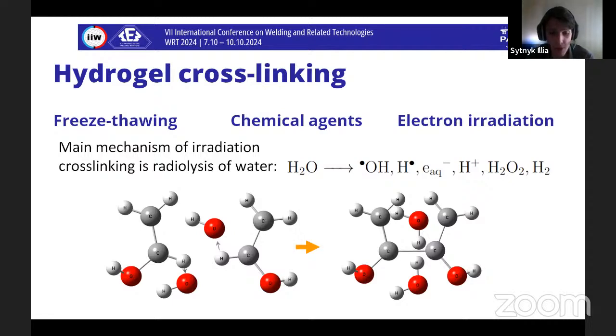In case of electron beam irradiation of hydrogel material, accelerated electrons are almost completely absorbed by water, which constitutes around 85% of its mass. Of the three main reactive forms that are produced in water during irradiation, which are hydrated electrons, hydroxyl radicals, and hydrogen atoms, hydroxyl radicals have the greatest impact of transferring reactivity from water to polymer chains. They detach hydrogen atoms from macromolecules, resulting in formation of macroradicals. That is, hydroxyl group, OH, can capture a hydrogen atom from the polymer bond, forming a water molecule.